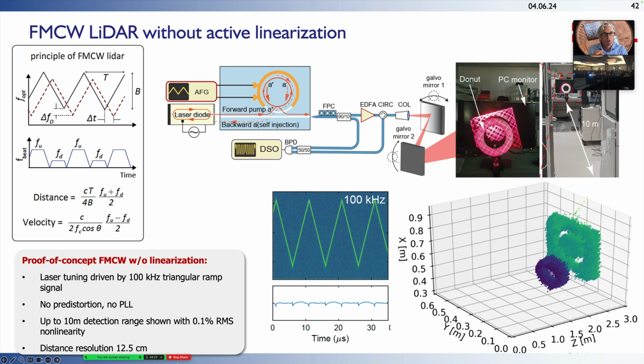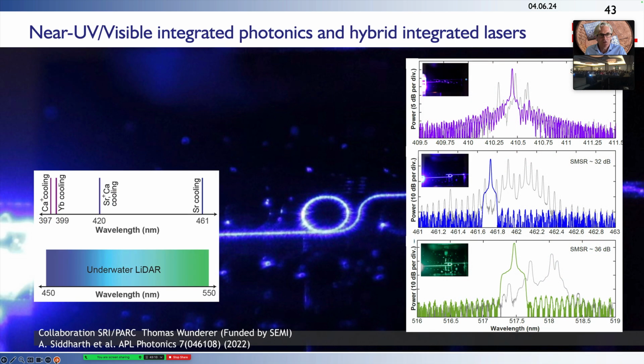But it's been compounded by a very stringent requirement on linearity. And with these aluminum nitride actuators, the linearity actually is excellent, less than 0.5% or even 0.1. And you can achieve here, for instance, very simple imaging of objects in the room and also infer their velocity. So this is really one of the directions. This frequency agility can also be extended to other wavelength ranges.